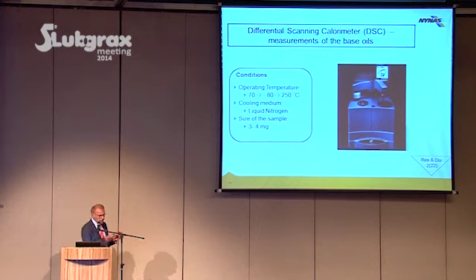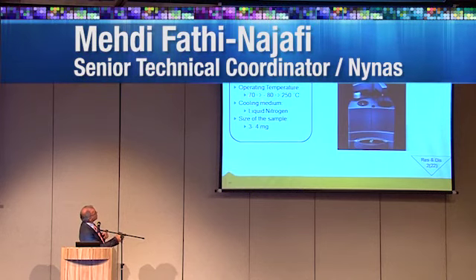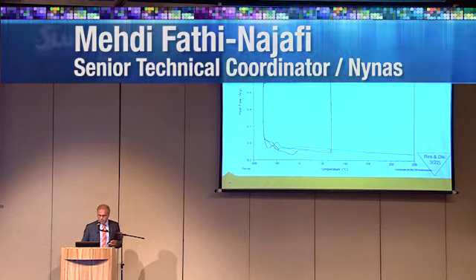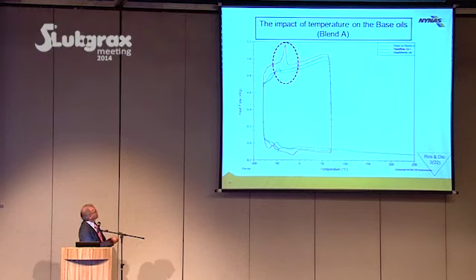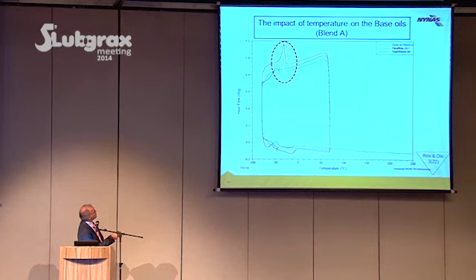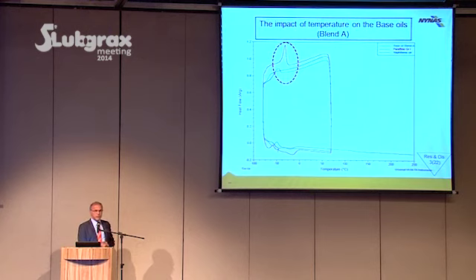So what we did is, the oil has been cooled down to -80 and then heated up to 250. What we see here, the red one is group 1, paraffinic. The blue one is the naphthenic, which we use, and the green one is the mixture. This peak represents wax crystallization.